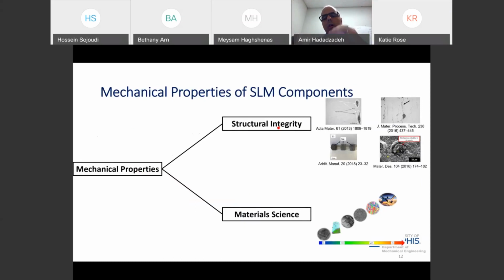So there are two perspectives in studying the properties, or specifically the mechanical properties of SLM components. We either study them based on the structural integrity or from material science. When we say structural integrity, it means we are trying to eliminate different types of defects that can form in the material, like porosities and holes in the sample, cracks like this case. Also, the surface roughness is another problem in SLM materials, because again, SLM is supposed to fabricate near net shape components. So if we find a way to reduce the surface roughness, it's good for some specific applications, specifically when we have fatigue. Because for fatigue, a rough surface is not a good option.